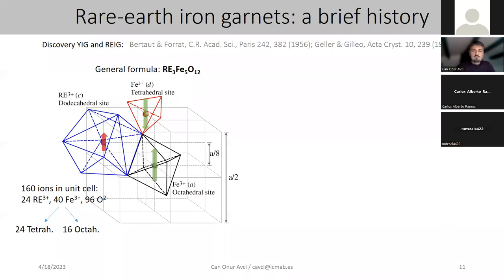In the complex unit cell of garnets, magnetic ions occupy, this iron 3+ occupy this site. So there's a complex unit cell, but in the simplistic scenario, you have these three occupation sites. One is a tetrahedral site, one is an octahedral site. You have the iron ions, which are coupled anti-parallel to each other, so they have anti-ferromagnetic coupling. And you have this third site, which is the dodecahedral site.